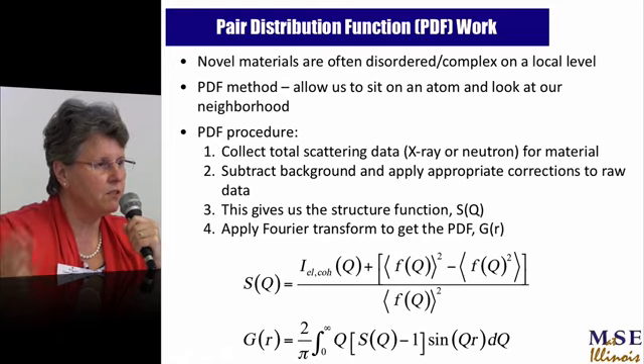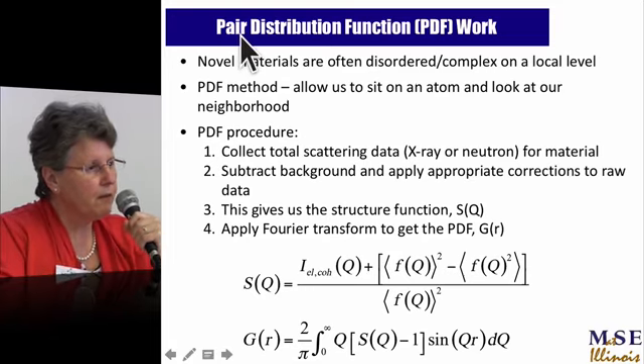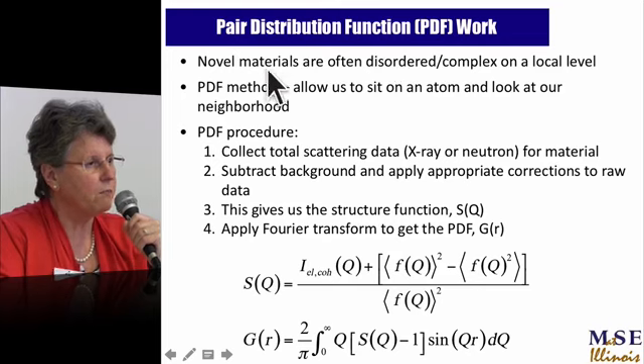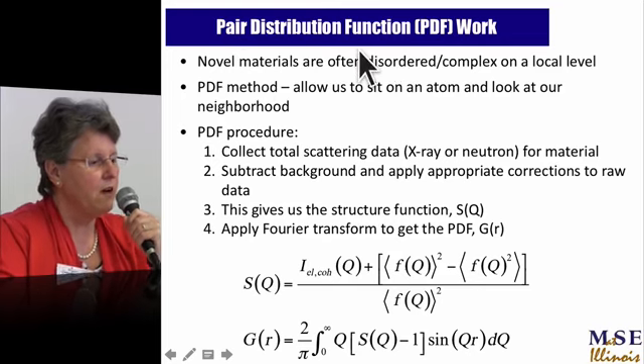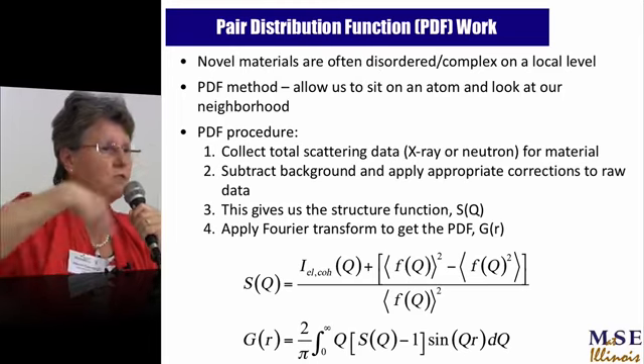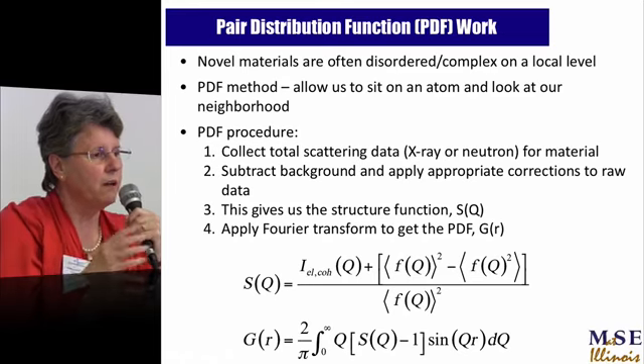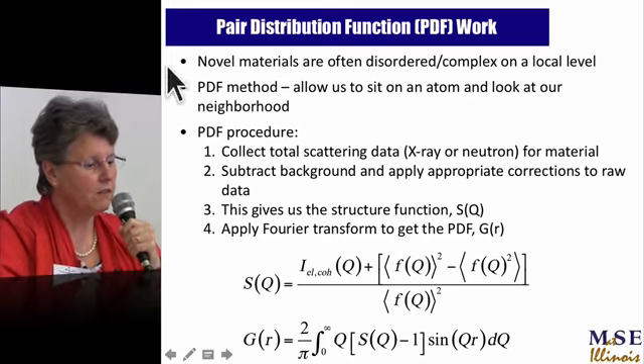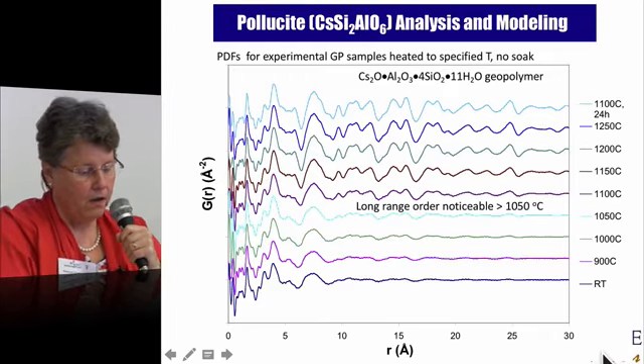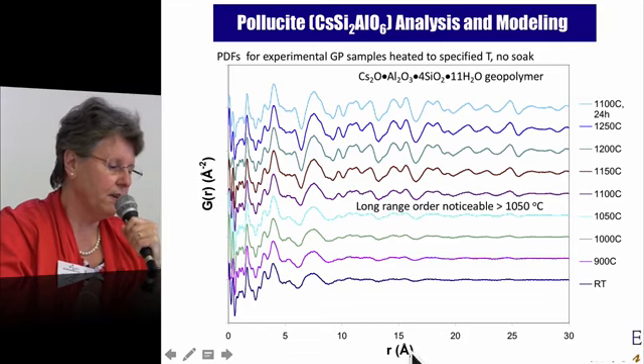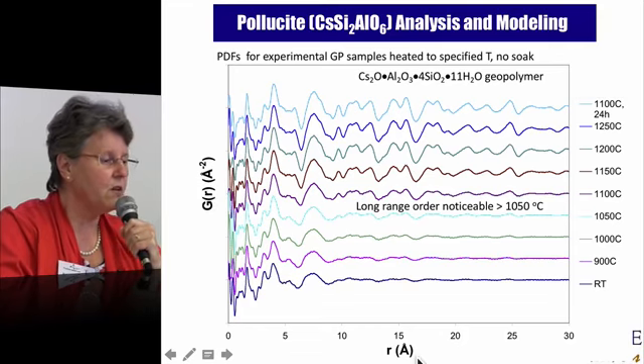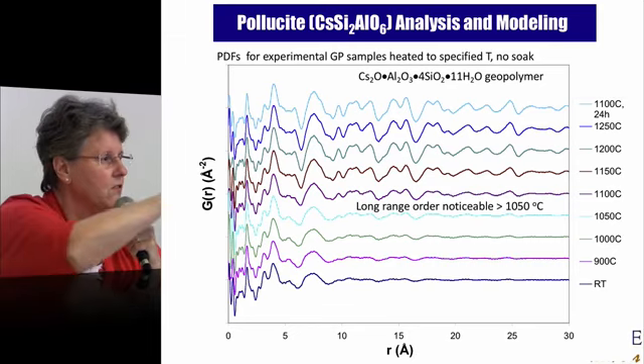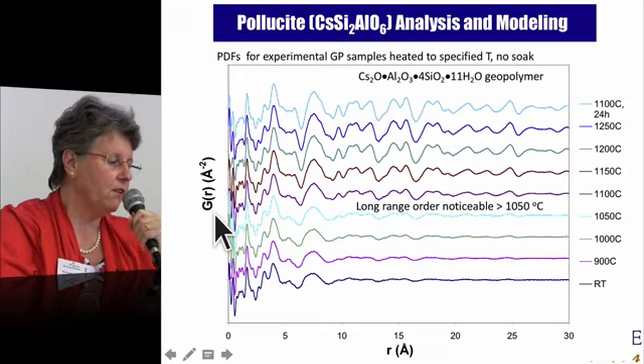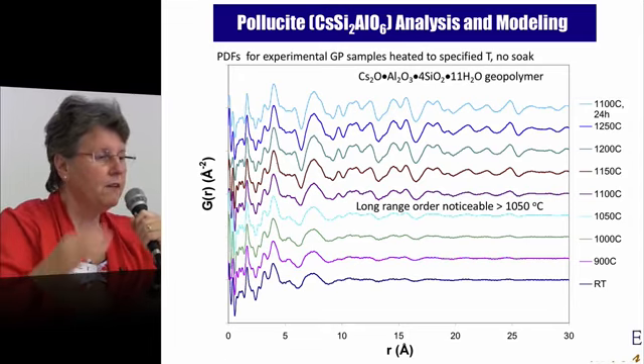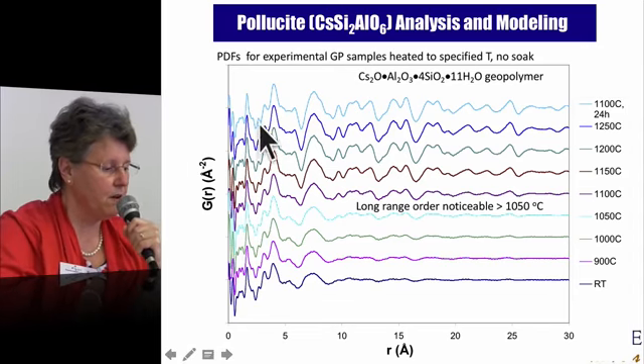So, well, meanwhile, moving on to the structure, we see as black and white in the TEM, and then we reach the limit of high resolution TEM. So we switch to radial distribution function in glass, or in the synchrotron work, it's pair distribution function, PDF. And that means you have one atom, and it measures the distances to all the other atoms in the material and what types of distances are there. It's an amorphous technique, and basically you get a histogram of characteristic distances with all the other atoms, and you get this function in real space.